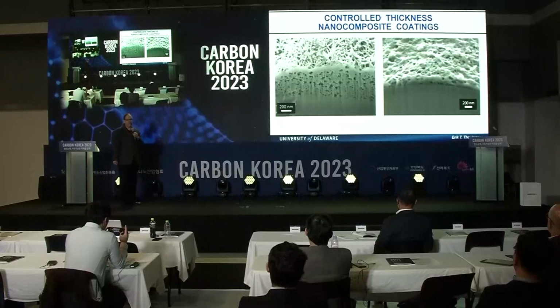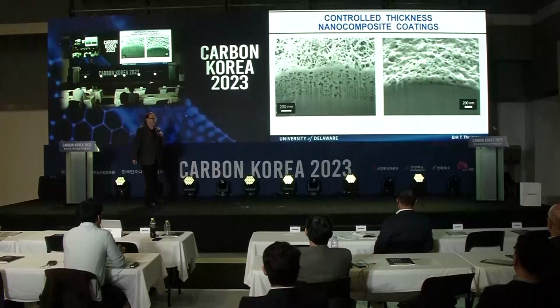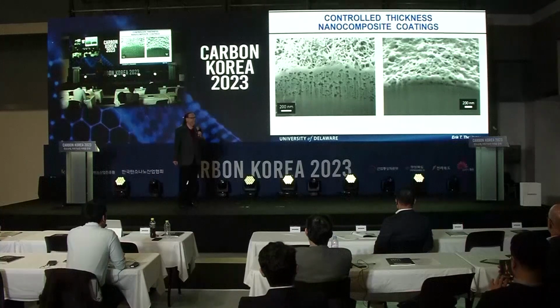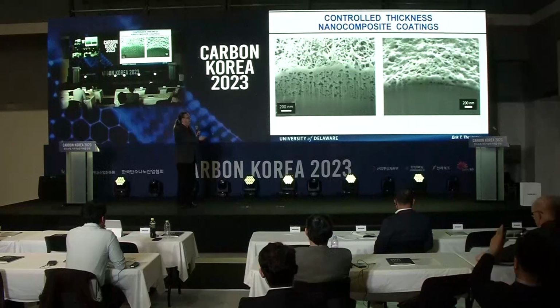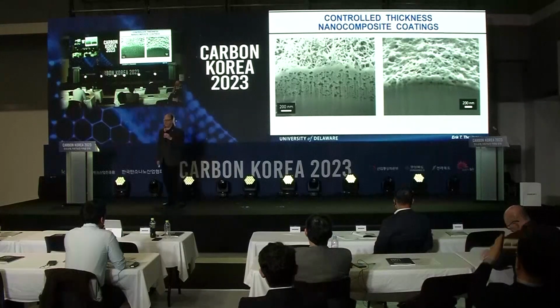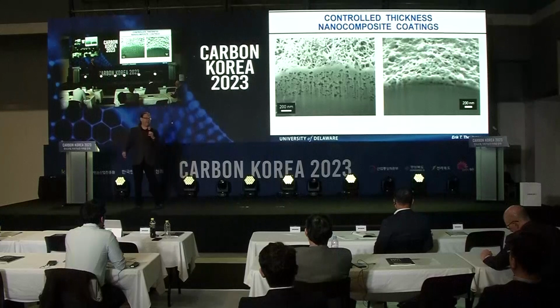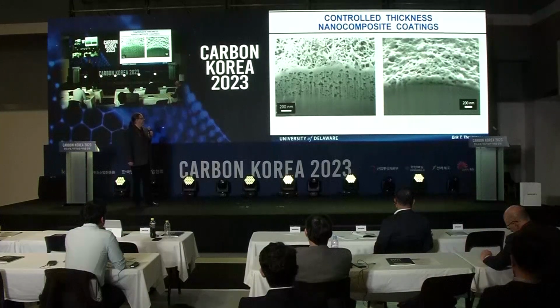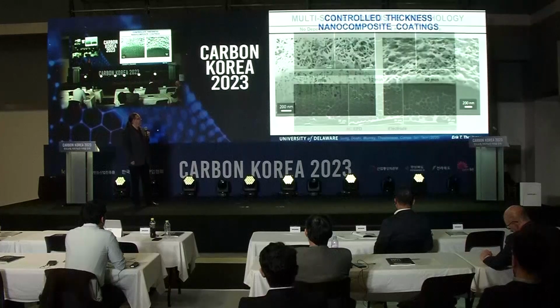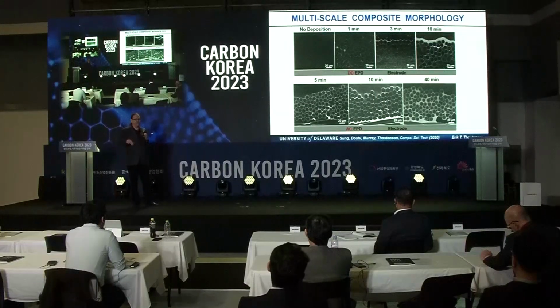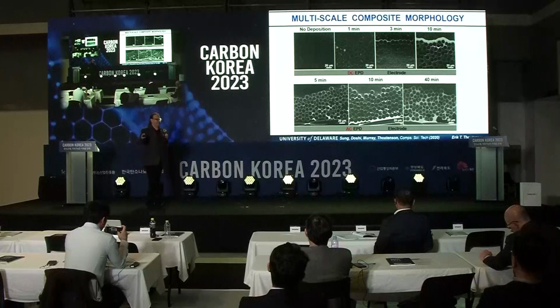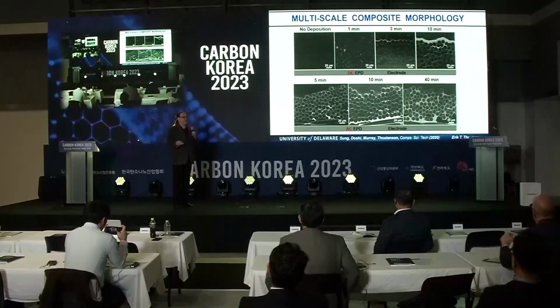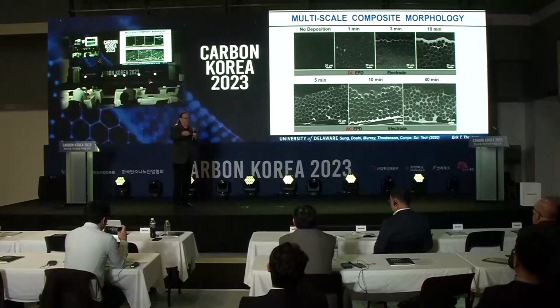We can also control this process quite a bit. We can control the coating thickness. On the left-hand side, you see a coating which is in the few hundred nanometer range, and on the right-hand side, less than 100 nanometers. So again, you see that porous type of coating. I could spend an hour talking about this, but we have a good understanding of how we can control the location.